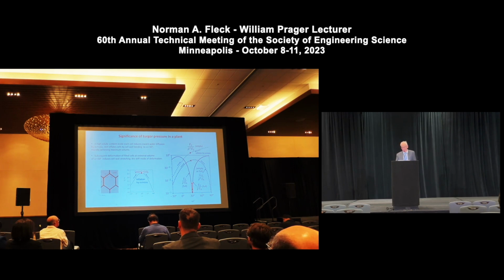So that is the shear response. The shear modulus scales with relative density cubed as a function of omega. So this is the shear response either of an empty or of a filled honeycomb. If, on the other hand, I ask the question, what is the axial response, as opposed to the shear response? If the honeycomb is empty, again, the modulus scales with relative density cubed, and here's my dotted line